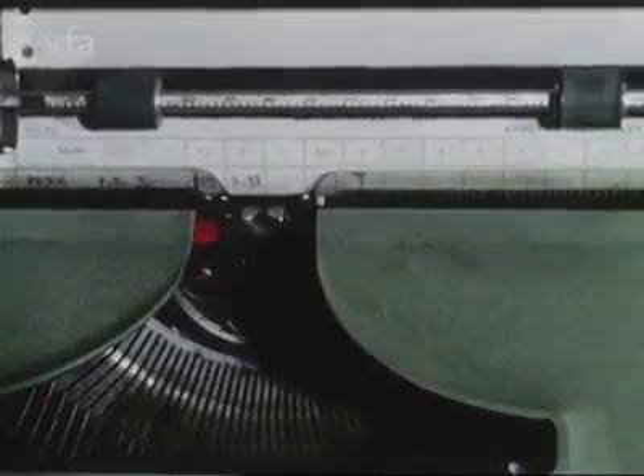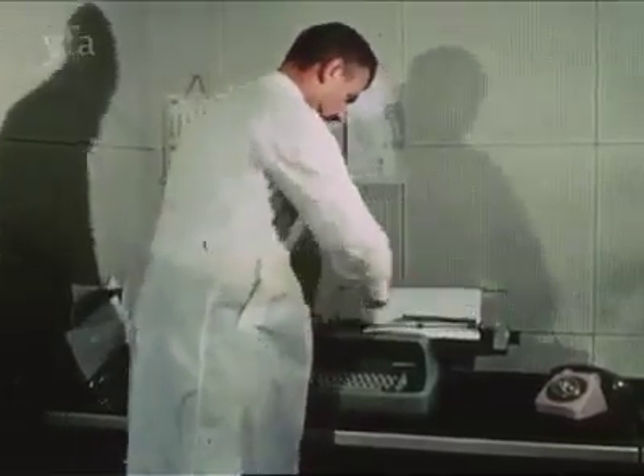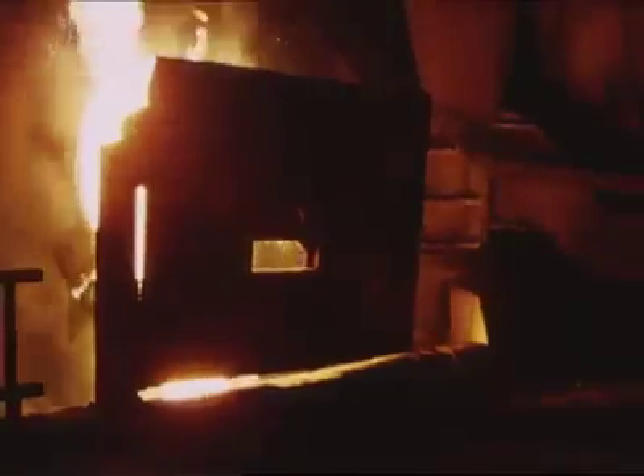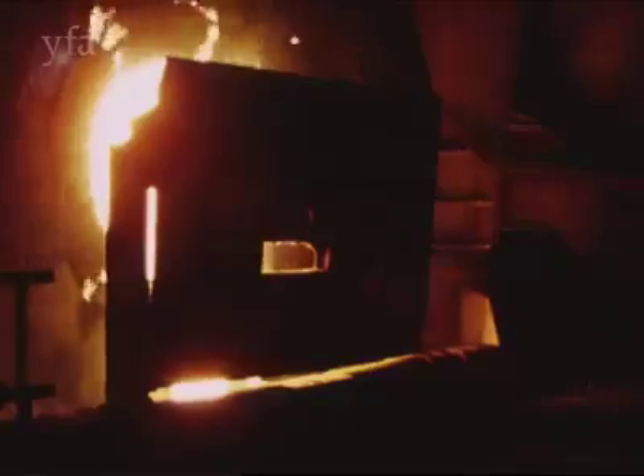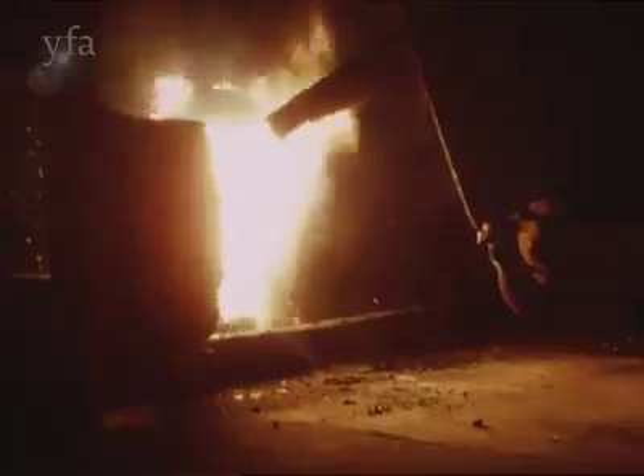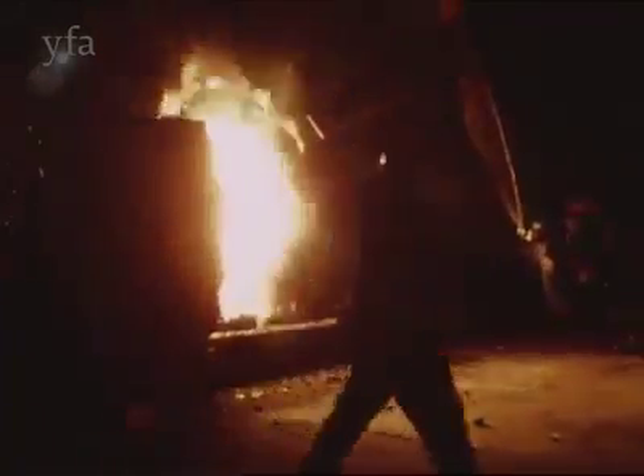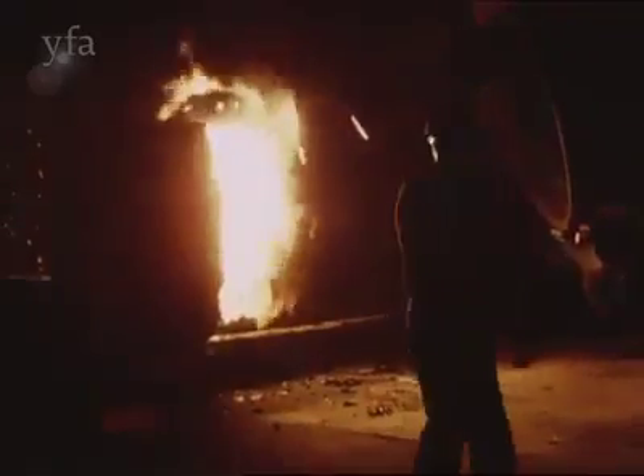A copy of the report is sent back to the steelmakers without delay, and they have all the information required within a few minutes of dispatching the sample. Back at the Kaldo, a final temperature check is made, and once the correct conditions have been established, the metal is tapped into the waiting ladle. Over 90 tons of high-grade steel are produced at each cast, and the production cycle can be complete in just over an hour. The deoxidation and alloy additions are made to the metal stream during tapping.